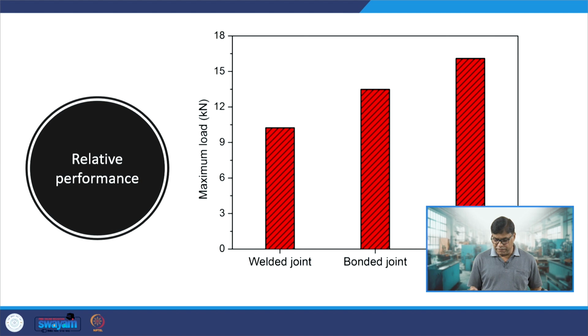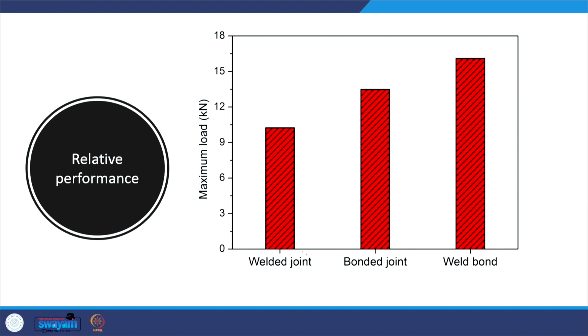If we compare the performance of the welded joints where we simply develop the spot weld by TIG welding, like this, then our joint strength is less, load carrying capacity is say around 10 Newton. If we use bonded joints, meaning only the adhesive bonds, then our load carrying capacity is around say 13.5 Newton. Okay. And if we combine both the adhesive joint and the weld joint, then our load carrying capacity is enhanced further.